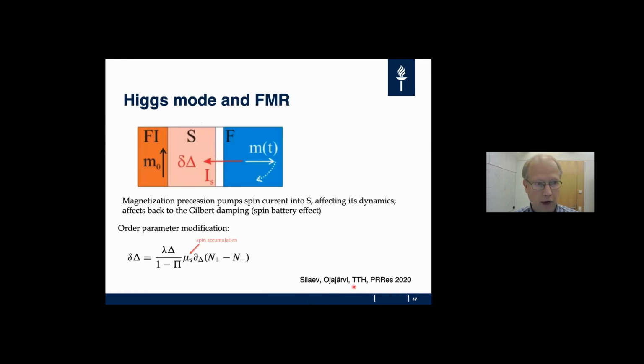An alternative way to access the Higgs mode in principle is to study its coupling with the ferromagnetic resonance, where the spin current driven by the Higgs mode is coupled to the ferromagnetic resonance mode. This would show up as a peak in the Gilbert damping at the frequency of the Higgs mode.